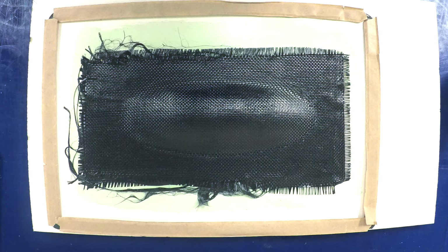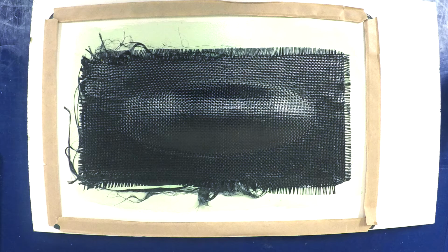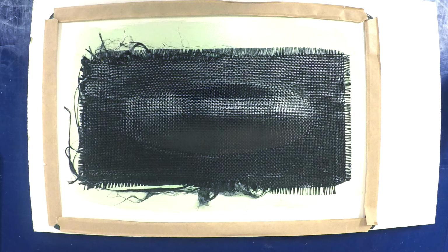Composite products usually produce better results when used with two-sided molds and are subject to pressures during curing. These pressures allow for a tighter fit around the mold, and they also help with removing any air or gases from within the product. This is the most common process in professional applications.